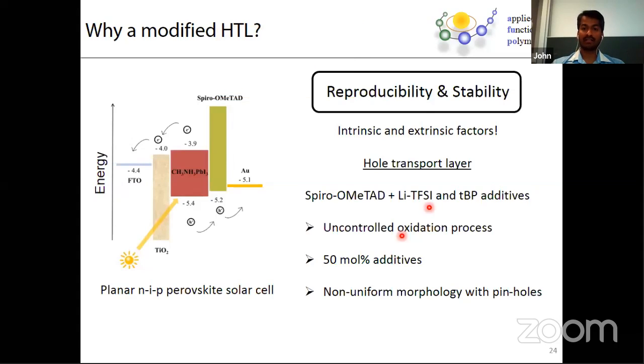And the other important factor here is that lithium TFSI is not a direct redox couple for spiro-OMeTAD. It basically helps with the oxygen. So it helps the spiro-OMeTAD react with atmospheric oxygen and then get oxidized naturally. So there is no control of the oxidation process over time. And so there is no reproducibility for the device performance.